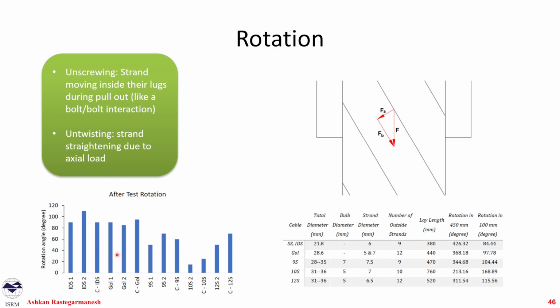As you can see, our plain cables tend to be around 80 to 100 degrees rotation after the test, but our bolt cables tend to be much lower, but with more variability. And it's very interesting because for SS, IDS, and GUL cable, we are looking at values very similar to the mean of these values. But for our bolt cables, we should be getting more, between 100 to 168, but we are getting less. This suggests that bolt cables are damaging the grout. So during the test, some of the rotation is actually getting lost by unscrewing that happens inside the grout column.